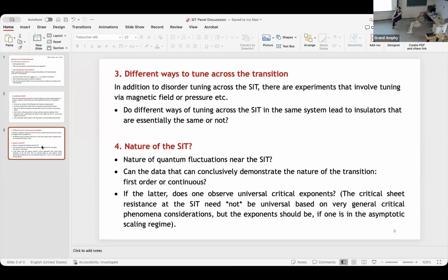I mean, the resistance scaling is probably also a difficult topic, but say when you want to get specifics, the question is how deep you can go towards the presumed quantum critical point until this other state takes over. It could be that something similar happens in both materials, and maybe we go a bit farther toward the point, but then we also see this reentrant behavior in the resistance, which seems to indicate that eventually it's not continuously vanishing. And I think the difficulty is that you have so few points in the critical regime. So now, concerning the experimental status, the future will show whether we can more accurately map out this area and see what other things happen.